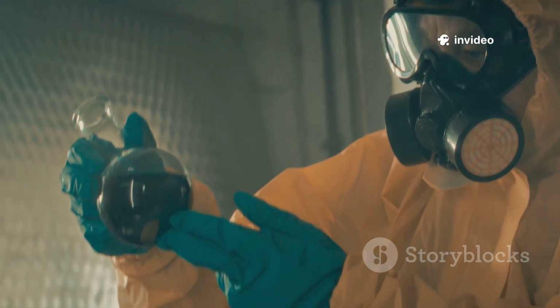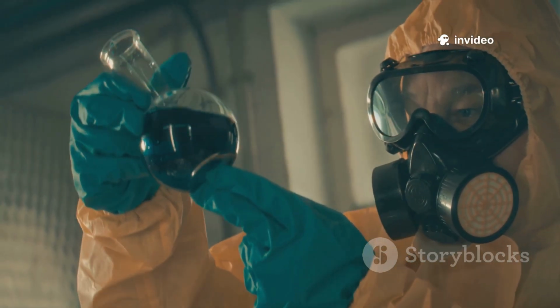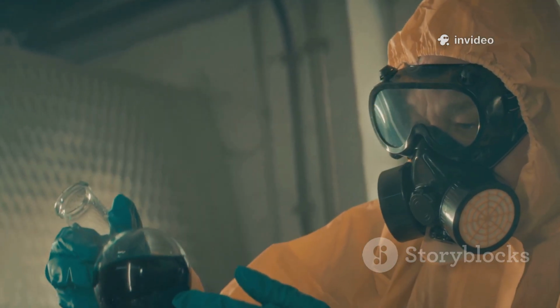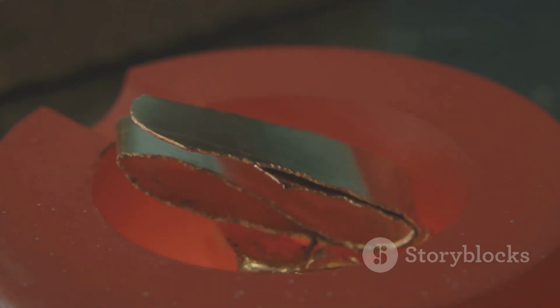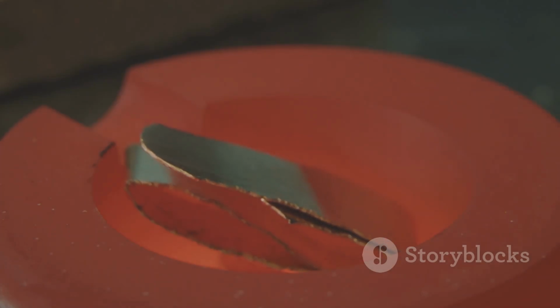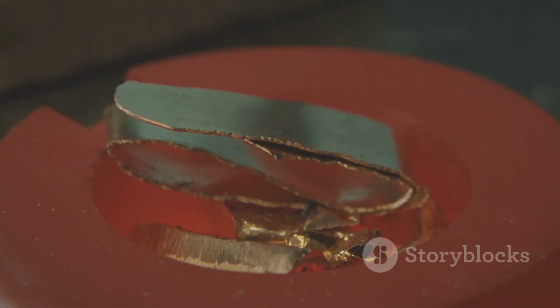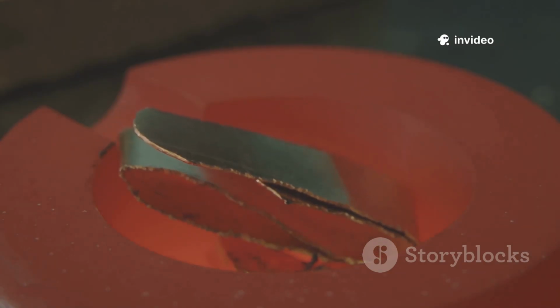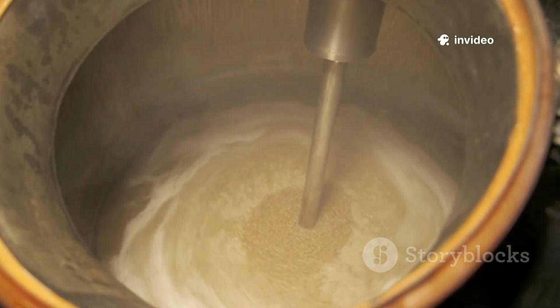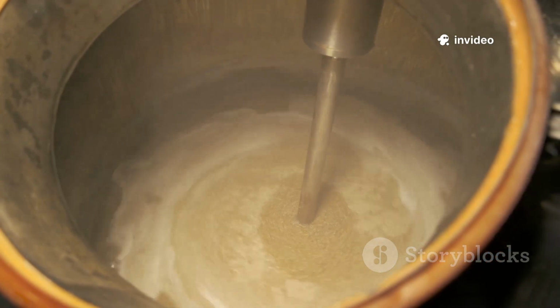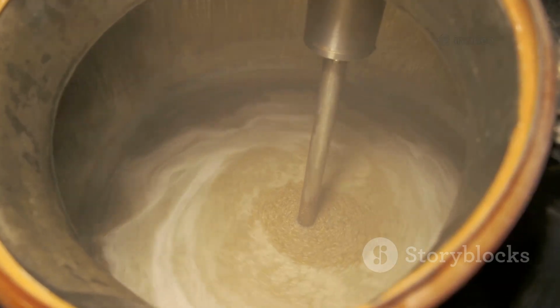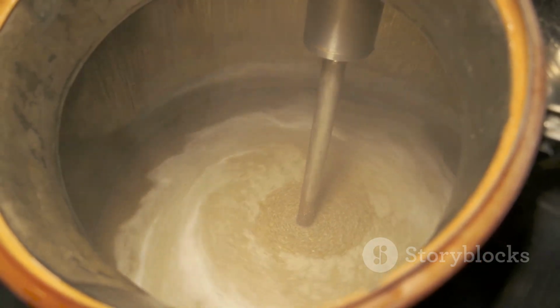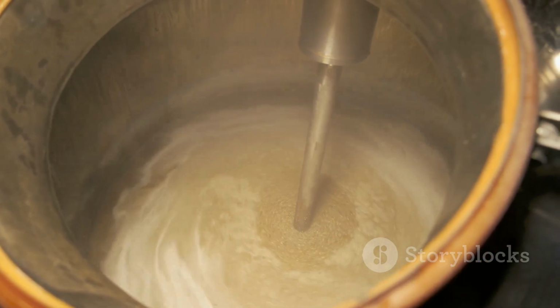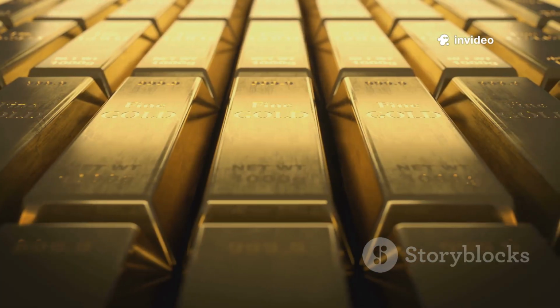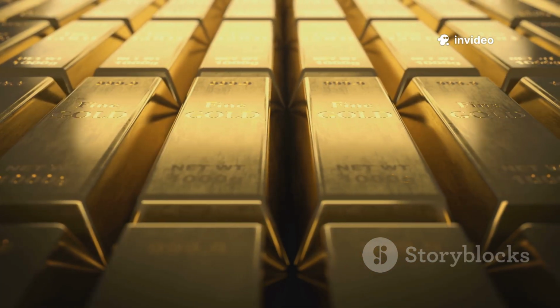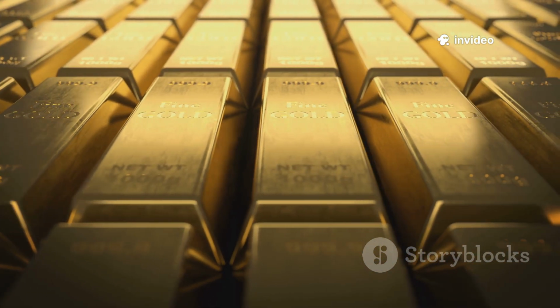This might sound dangerous, and it is, which is why it's handled with extreme care in a highly controlled environment. The cyanide performs a special chemical trick. It dissolves the gold. As the slurry is gently stirred in these massive tanks, the cyanide solution gets to work. It latches onto the gold particles, forming a water-soluble gold cyanide complex. In simple terms, the solid gold disappears from the rock powder and becomes part of the liquid solution. All the other minerals and rock dust, which don't react with the cyanide, remain as solid particles.